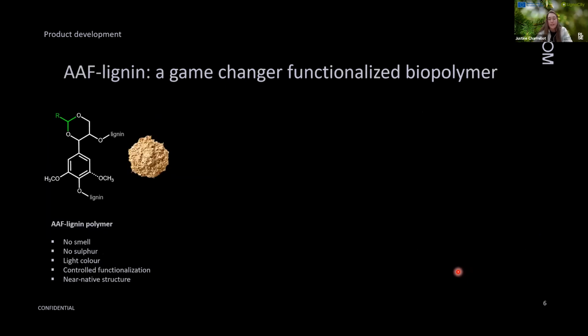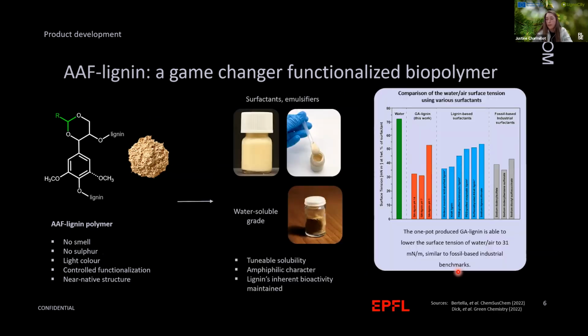Then there's another interesting field of application that we can use this lignin for. We'll mention this quickly. It's as a surface active molecule. So we are really able to perform emulsions with it, use it as a surfactant, because this lignin can have an amphiphilic character, and we can also play with this functionalization. We were able to have a water-soluble grade of this lignin, and it was shown that the GA lignin is good in terms of surface tension reduction, which is what we want for a surfactant. So this is the water-air surface tension. The GA lignin, under certain conditions, compares to the fossil-based surfactant and also outperforms the other lignin-based surfactant.